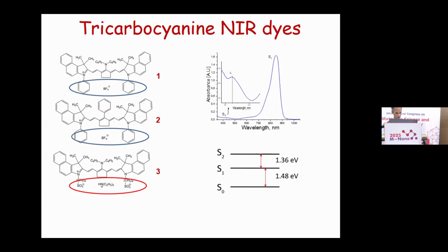If we look at the absorption spectrum of these dyes, they have fundamental absorption in the near infrared, around 900 nanometers, and also they have S2 absorption in the green, in the blue region of the spectrum. From this data, we can reconstruct the energy levels. The separation between the S1 and S2 energy levels is rather large, which is good. That means that we can observe Anti-Kasha emission in these compounds.